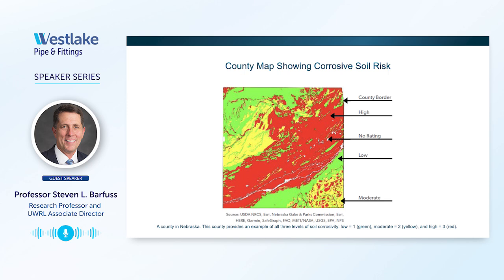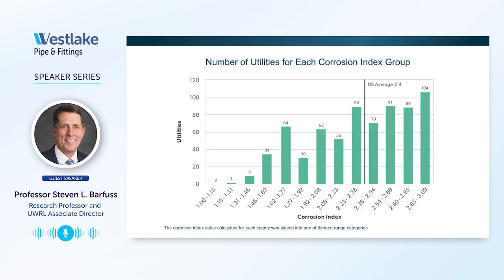So this is a county in Nebraska, just to show you an example. We found the boundary of the county. We used ArcGIS to then quantify the soil corrosion index, as we called it, based on a 1, 2, and 3 and the number of colored pixels in that county. And in so doing, we came up with a range of corrosion indices. These are equal width ranges, and the number of utilities associated with each of those corrosion index ranges. And you can see here's the average corrosion index for the US, and those utilities that are higher and lower.